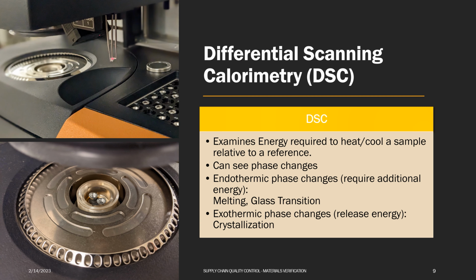Differential scanning calorimetry, usually referred to as DSC, is an instrument where you basically put a small amount of your material, usually 5 to 10 milligrams, into an aluminum DSC pan and have an empty pan next to it, and the instrument measures the amount of energy required to heat up your material compared to that reference pan. You can see phase changes because things like melting the material or moving through glass transitions require extra energy input to keep that heating rate. And then you can see exothermic processes like crystallization when you cool the material.